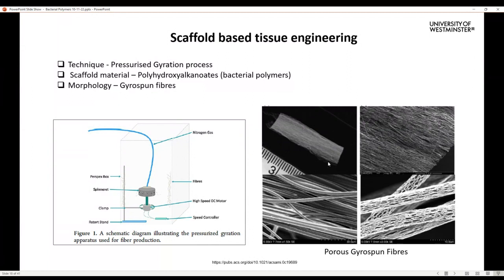I have put the optical image of the fiber here, the first image, and the SEM, or the scanning electron micrograph. You can see these really nice porous fibers. Now, what did we do with these fibers? We used them as a three-dimensional scaffold to culture cells. Now, instead of growing human cells on a flat two-dimensional plastic surface, when we culture them on a three-dimensional scaffold, they're able to interact with each other. This environment is able to mimic the in vivo condition, human body-like condition, basically.